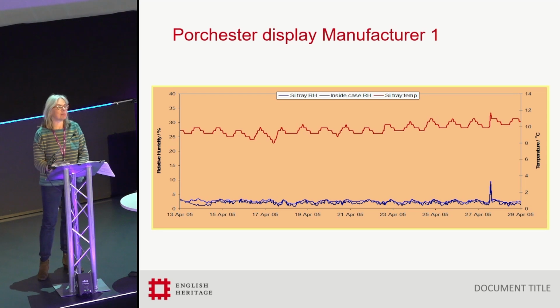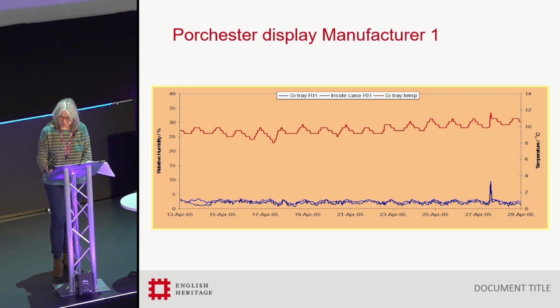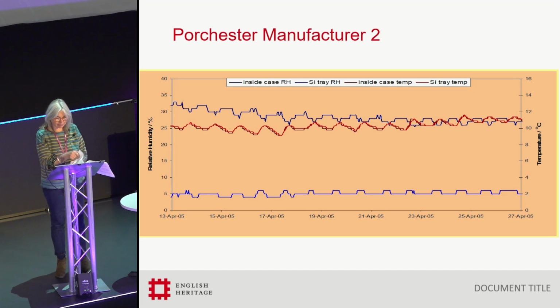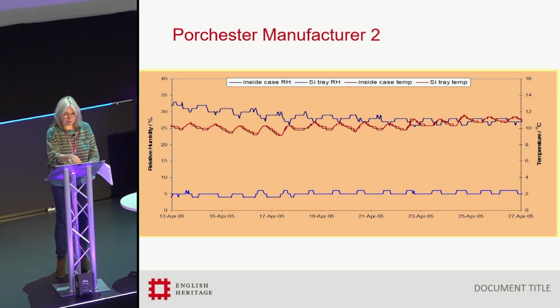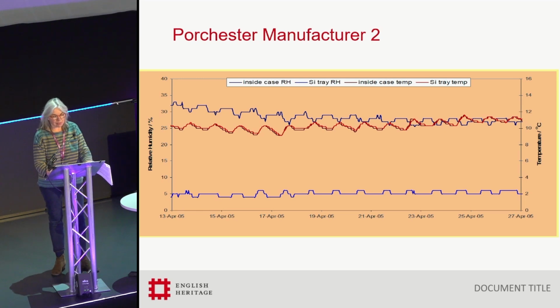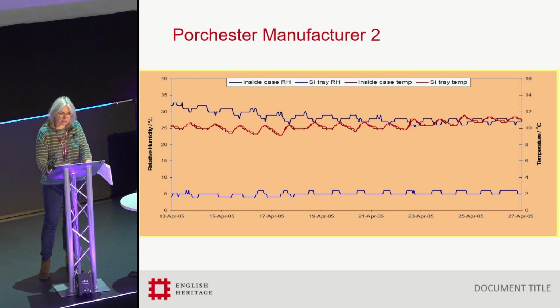With introducing 8mm holes throughout the baseboard of the case, you get the RH of the display volume more or less corresponding to the RH in the silica gel drawer, which is what we want. It's the bottom two lines of this graph. And this slide shows the same case as previously, but with smaller 5mm holes in the baseboard, and illustrates that the size of the baseboard holes make a difference with exchange, and that 5mm holes don't work. The case volume reading about 30% RH, compared with the silica gel unit of around 5%.